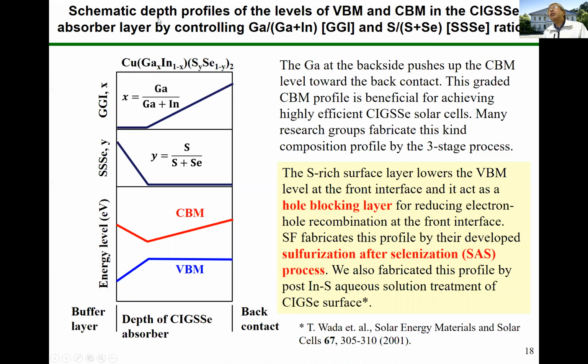This is the schematic depth profile of the level of valence band maximum and conduction band minimum in the CIGSSe absorber layer by controlling GGI and S/(S+Se) ratios. This is a popular band profile. A sulfur-rich surface layer lowers the valence band maximum level at the front interface, and it acts as a hole blocking layer for reducing electron-hole recombination at the front interface. We also fabricated this profile by post-indium sulfide aqueous solution treatment of the CIGSe surface.